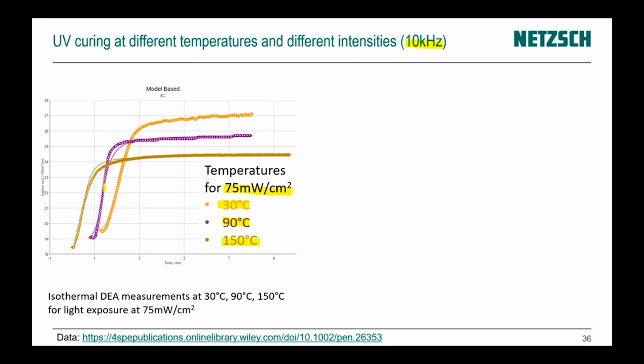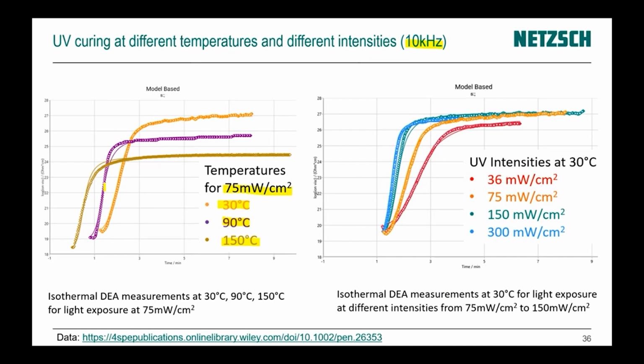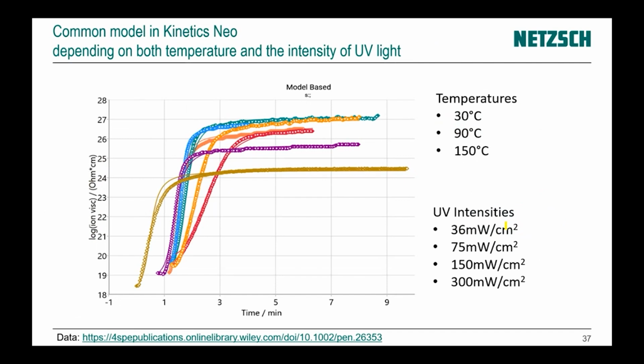But if we take a constant temperature but different intensities, then we can see that the reaction rate is also different. The slowest one is for the lowest value of intensity, and the fastest one is for the highest value of intensity. In our software, we are able to create one common kinetic model, which shows how our curing rate depends on temperature and on UV intensity. And here are our results, and you see that the experimental data and our model are mostly in agreement with each other.